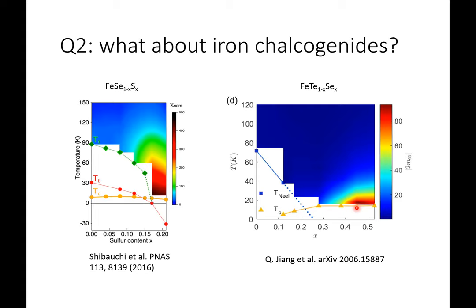I would argue that this bodes well to the idea that instead of the nematic phase competing with superconductivity, it's the antiferromagnetic ordered phase, the static antiferromagnetic ordered phase. Because everything that you see in the underdoped regime, the reduction in lattice parameter below Tc, is accompanied by the reduction in the static ordered moment below Tc as well. Right.